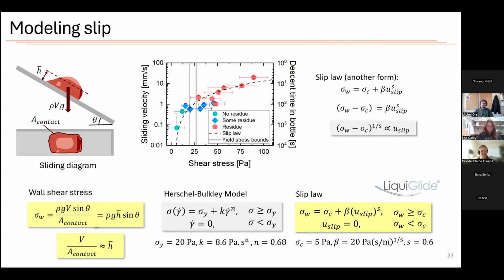Oh, residual stresses are really, really interesting. I think they're present in every yield stress fluid. So they're definitely present here, although I didn't measure them in particular. Usually residual stresses are about stresses that are retained by the material up to about 10 to 20% of the yield stress. So in this case, that would be about 2 to 4 pascals. I don't think those are playing a role in the residue that's left when the material slides. I think it's exactly what you said: if you have enough stress, then the material is sliding, but it is also under enough shear stress that it is above the internal yield stress and it is able to shear. So rather than sliding purely, it is sliding on a very thin layer of additional ketchup.